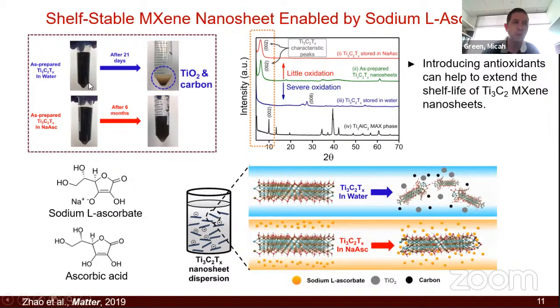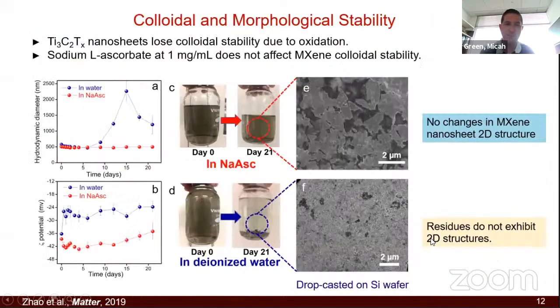So this is Xiaofei's work. You can see here's the original dispersion. And after 3 weeks, it's completely gone. But if you use something like sodium ascorbate, then after 6 months, you still have your dispersion. We've measured this in a number of different ways using XRD, as you see here. You see a big difference between when you have severe oxidation versus just a little oxidation when you have something like sodium ascorbate. And we even did simulations to show how these materials can fall apart in some cases versus staying together when you use something to protect them.